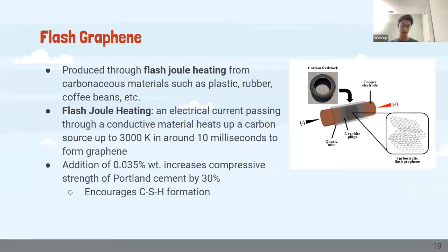Next slide. And lastly, I'd like to introduce flash graphene, which is a relatively less researched type of SCM. It's produced specifically through a process called flash Joule heating, where you take any solid carbonaceous material such as plastic, rubber, or coffee beans, and you subject it to an electrical current, which heats up the carbon material to 3000 degrees Kelvin in about 10 milliseconds. Essentially all the carbon-carbon atom bonds break and they reform to create graphene, or specifically, flash graphene.